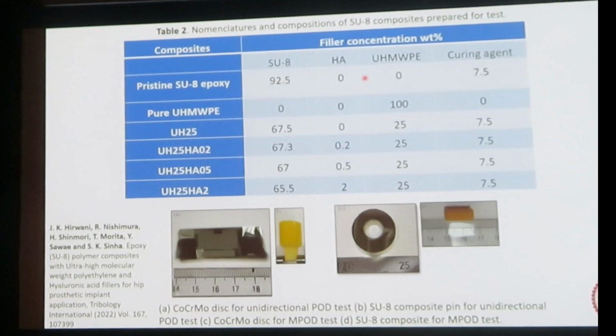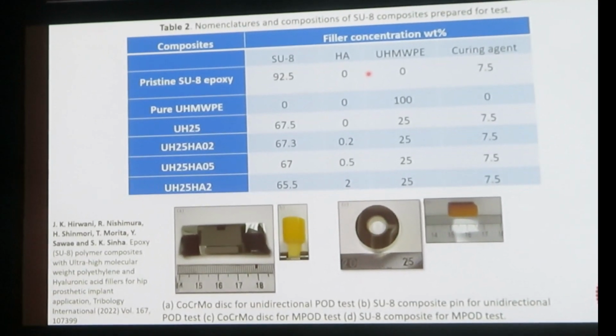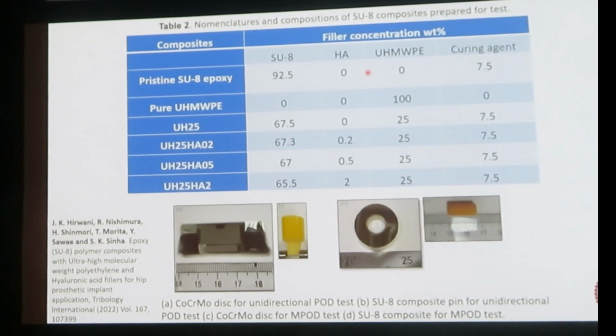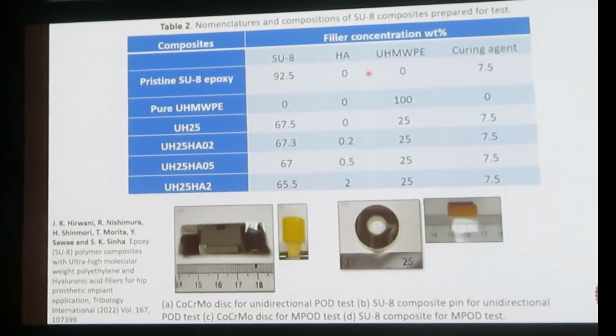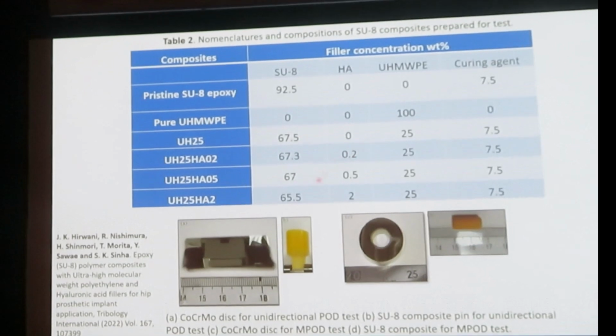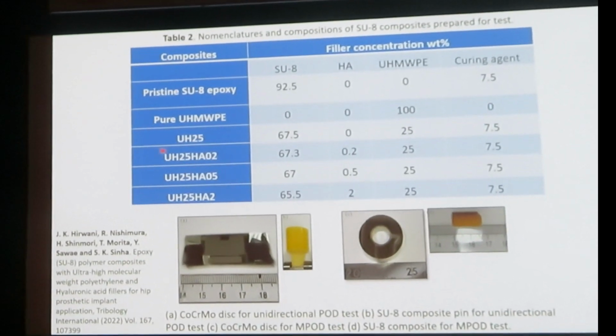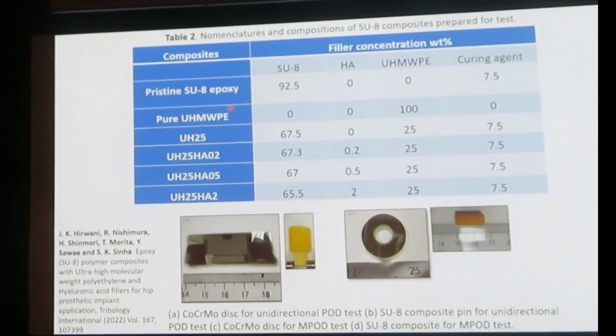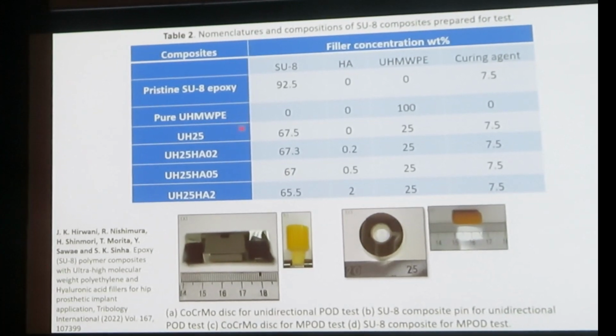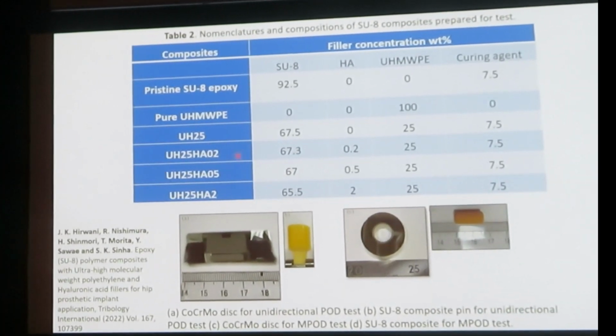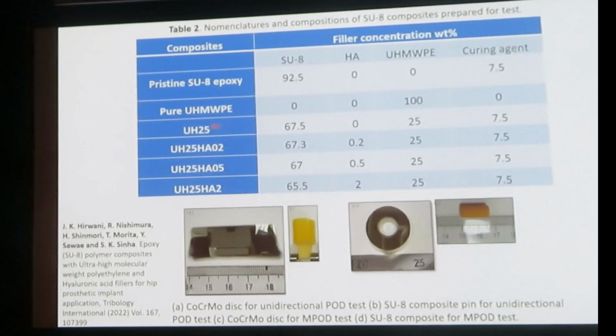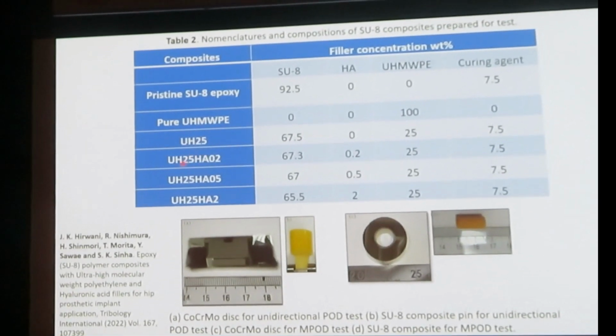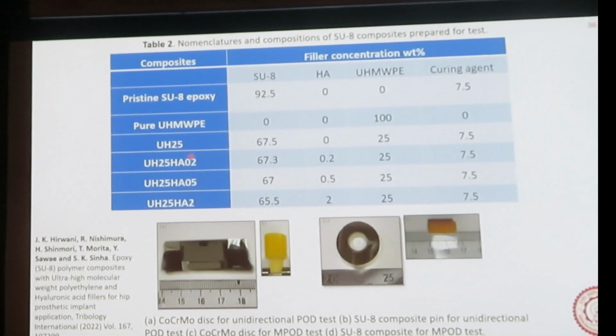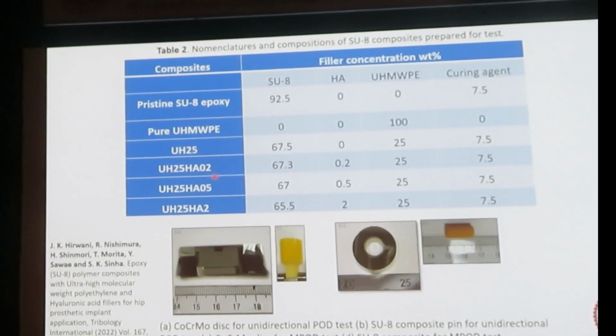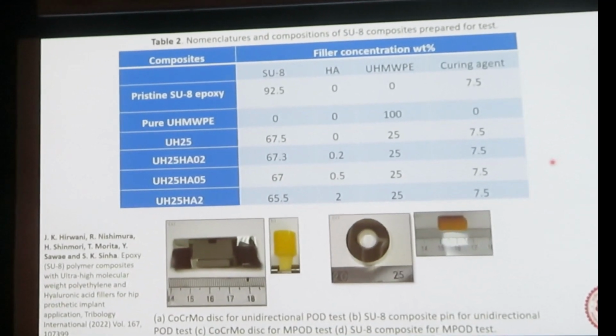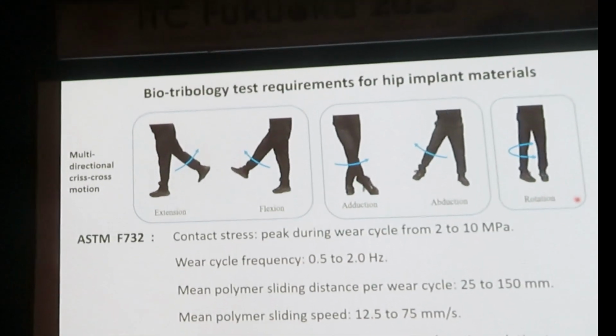And also we added HA, which is hyaluronic acid. Hyaluronic acid is a natural lubricant, and therefore it will help in this whole lubrication process. So the specimens are pristine SU8 epoxy, pure UHMWPE, and the mixed ones, for example, 25% of UHMWPE, and 25% of UHMWPE with 0.2% of HA added into it. These are the few specimens, and before we conduct the test,